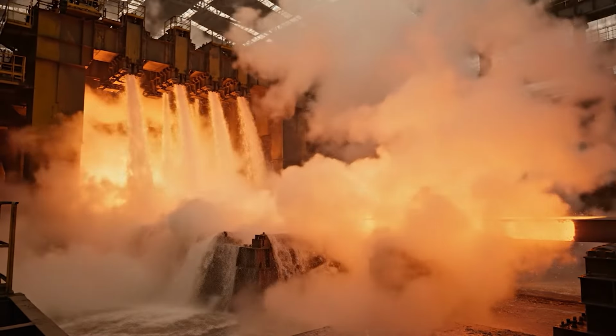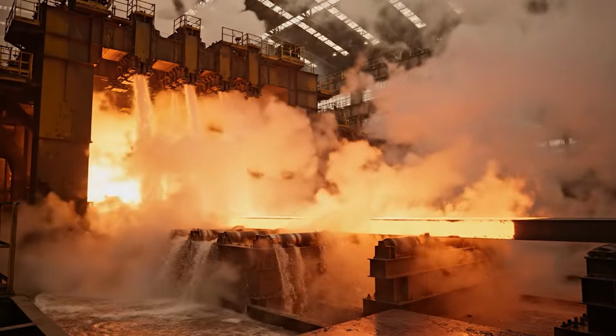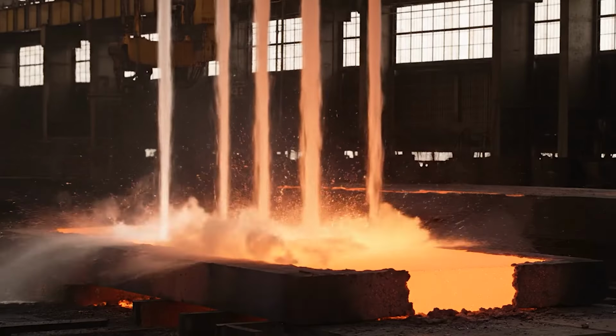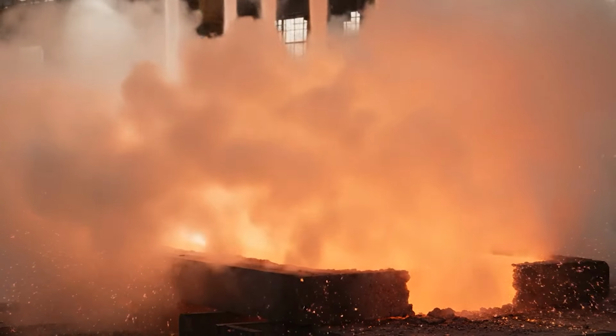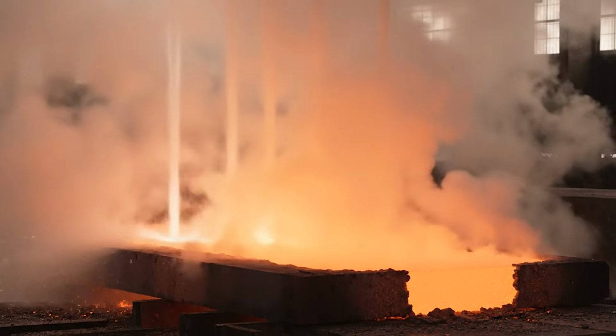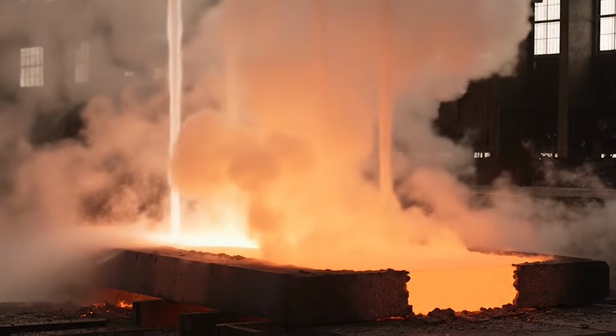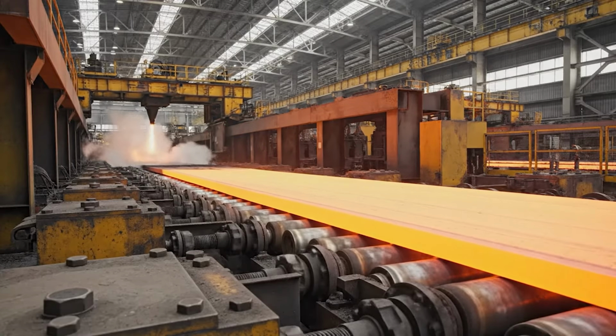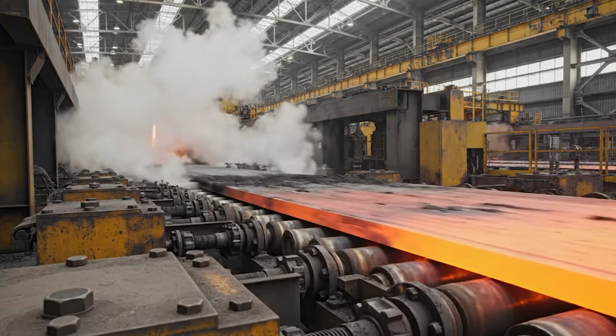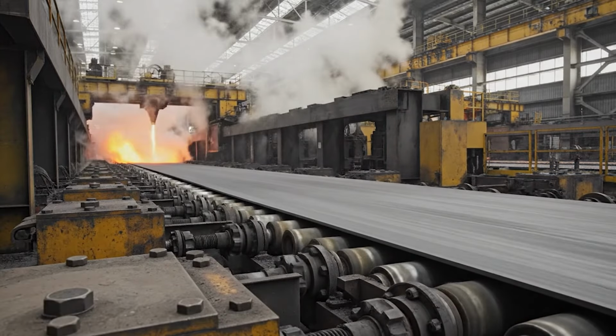Immediately after hot rolling, cooling begins. Rows of water nozzles spray the steel strip in controlled patterns. Cooling rates are adjusted precisely to control the steel's microstructure. This step determines strength, ductility, and toughness. The wrong cooling curve can ruin an entire coil. Steel science happens here, in seconds.